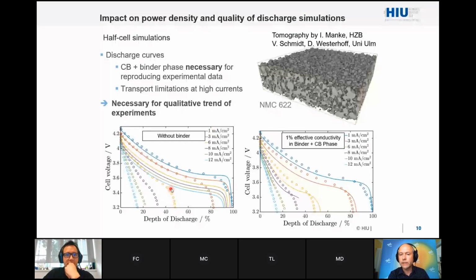If you included a binder, of course, we haven't been perfect in agreement, as was pointed out. I mean, these are still modeling assumptions. But the whole trend over a factor of 10 in the current density was recovered if we included the binder. So for the loss of capacity at large current, the binder was obviously a very important feature which we had to take into account if we want to understand what was going on in electrodes.